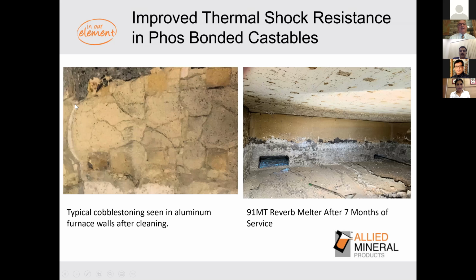Here you see typical cobblestoning in an aluminum furnace wall. Like I always tell everyone in my presentations, in my 40 years, if I get a call from a customer with a complaint, it's almost never about the lining wearing out prematurely. They didn't get the life that they expected due to wearing of the lining. Almost all the calls I've ever received have been about cracking. They've looked in the furnace and it's all cracked. Pieces are falling out. Maybe there's a large crack after dry out, things like this.